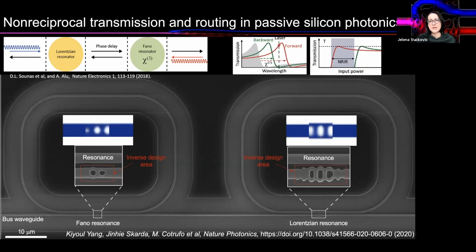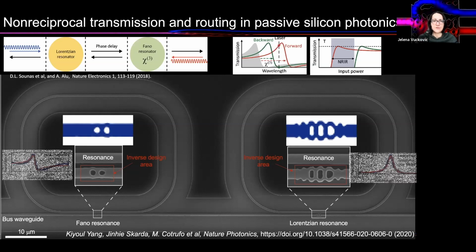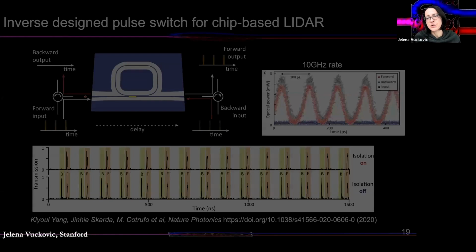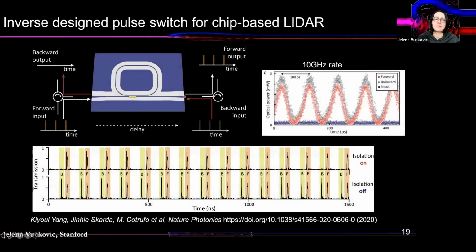And you see here how the optimization process looks like in these movies. They are designing pretty small regions, so that's why this doesn't take a long time. And when the optimization is done, these are the final optimized coupling regions. So you're just optimizing the coupler. You're not really affecting the resonator. And these are measured transmissions for Fano and Lorentzian resonators, which match theoretical performance. And then when you measure fabricated devices, we exactly see what is predicted.